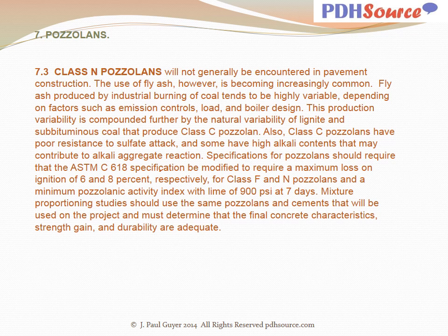The Class N pozzolans will not generally be encountered in pavement construction. The use of fly ash, however, is becoming increasingly common. Fly ash produced by industrial burning of coal tends to be highly variable depending on factors such as emission controls, load, and boiler design. This production variability is compounded further by the natural variability of lignite and subbituminous coal that produce Class C pozzolan. Also, Class C pozzolans have poor resistance to sulfate attack, and some have high alkali contents that may contribute to alkali aggregate reaction.